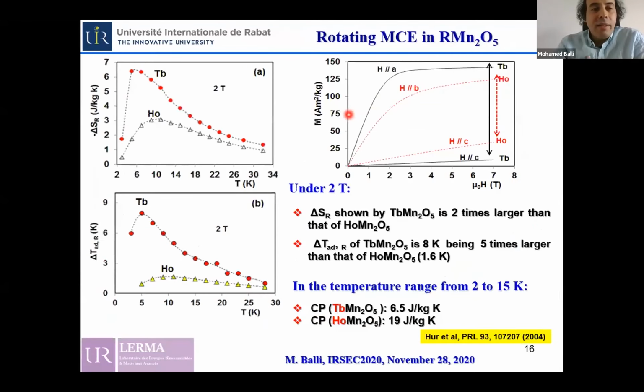In this slide is shown the rotating magnetocaloric effect in terms of both entropy change and adiabatic temperature change reported for terbium and holmium under a magnetic field of 2 Tesla. We can clearly see that the terbium compound involves better performance in terms of both entropy change and adiabatic temperature change.